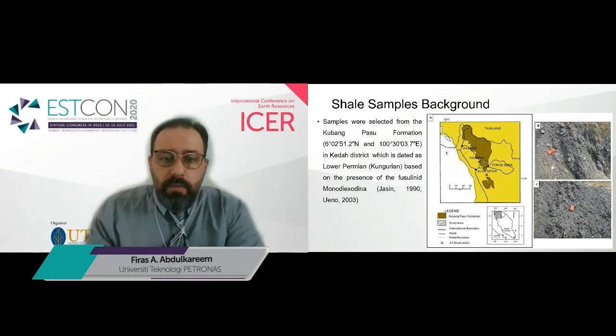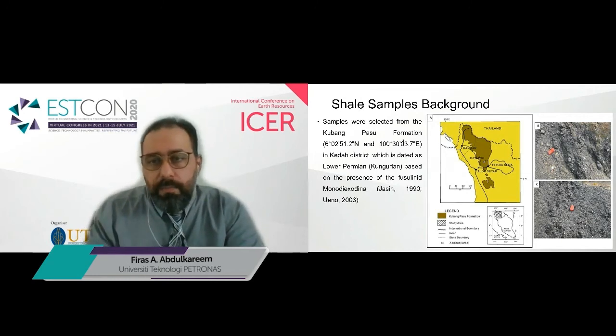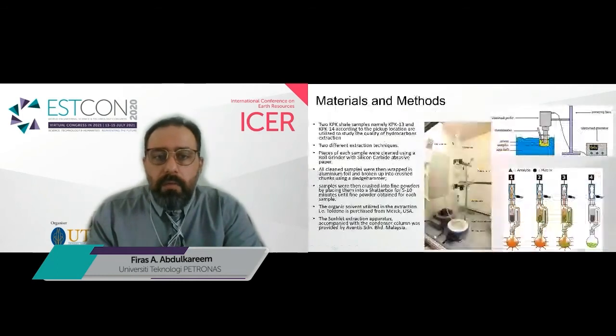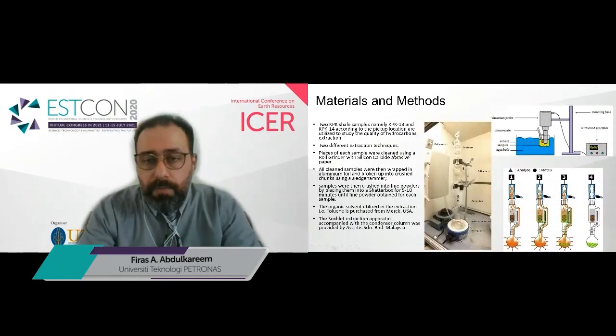The shale samples have been picked, washed, sieved, cleaned, and prepared for the extraction process. The extraction process has been split into two parts: the traditional way using the Soxhlet extractor and the ultrasonic accelerated or assisted type of extraction.